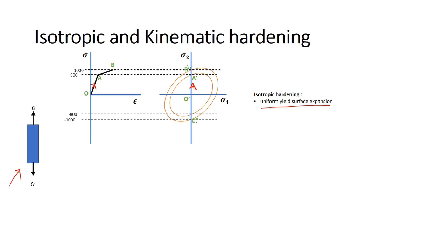With respect to the yield surface plot, we are on B''. Upon unloading, we go inside the yield surface, so we are in the elastic regime until we hit C' on the other side of the surface. At C' again, it starts to plasticize in compression. As we load further in compression to D, we have the new yield surface as shown.